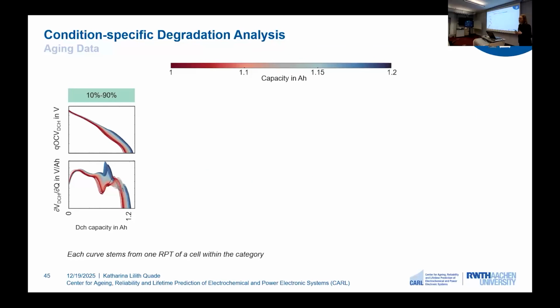So we want to compare these theoretical peak shifts now to our real data per cycling category. First, we need to have a look at our data. Here you can see the cycling condition 10% to 90% SOC. We can see here the voltage curves recorded during the reference performance tests and also the first derivatives. And each curve that you see here stems from one reference performance test of one cell within the category.